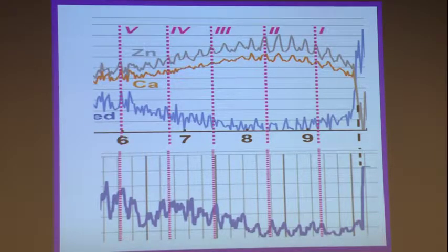So we see zinc matching with the calcium. The calcium is a strong signal over a strong background because there's a lot of calcium. Zinc is relatively low intensity there. It's the principal trace metal within teeth. And so we see all of these peaks numerically, and they also correspond exactly with positions of increased intensity.